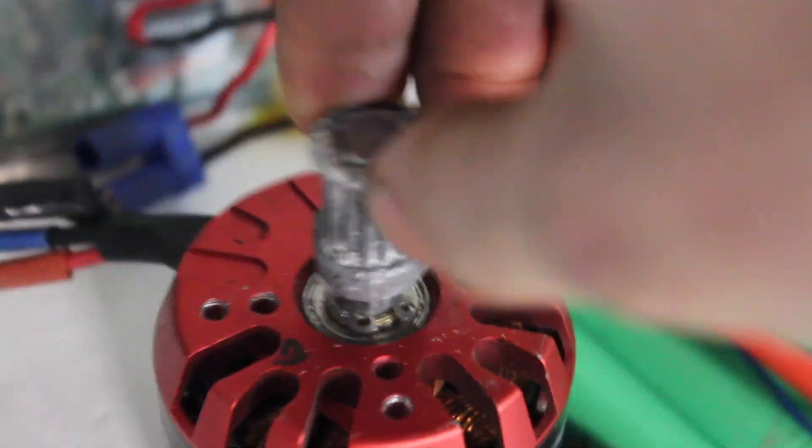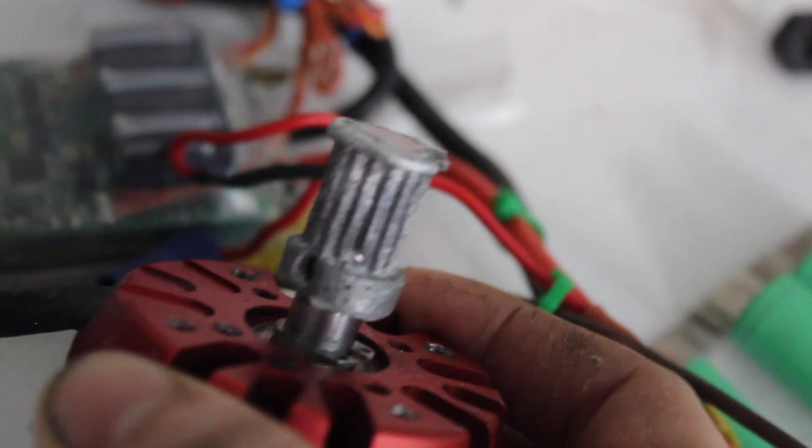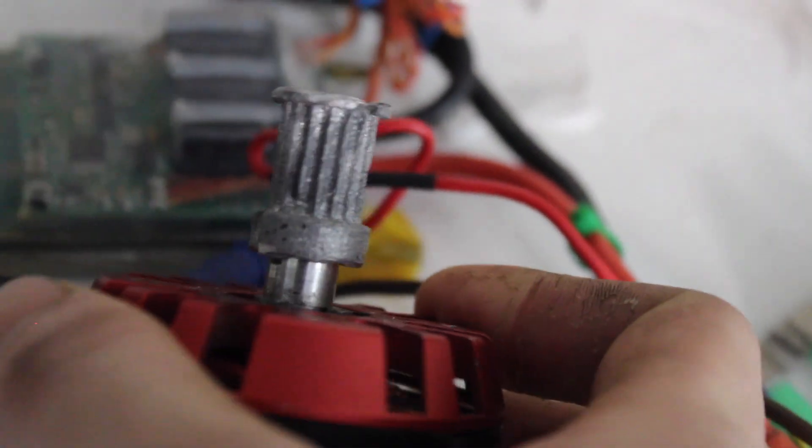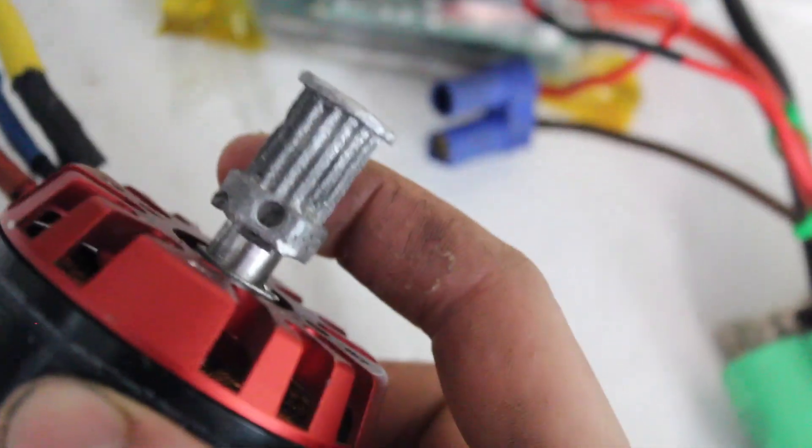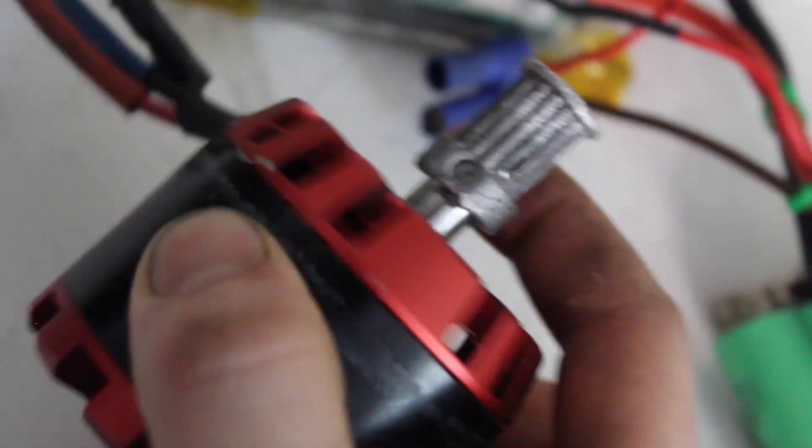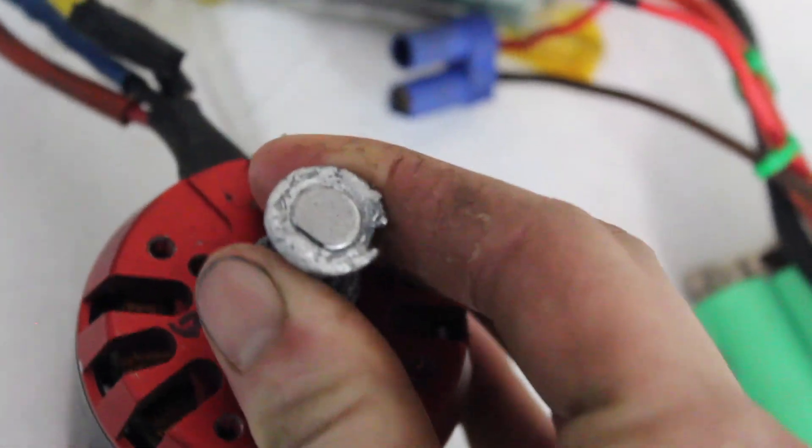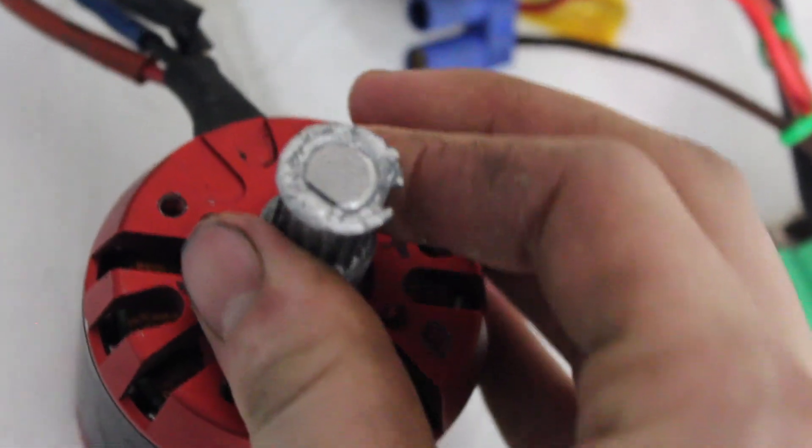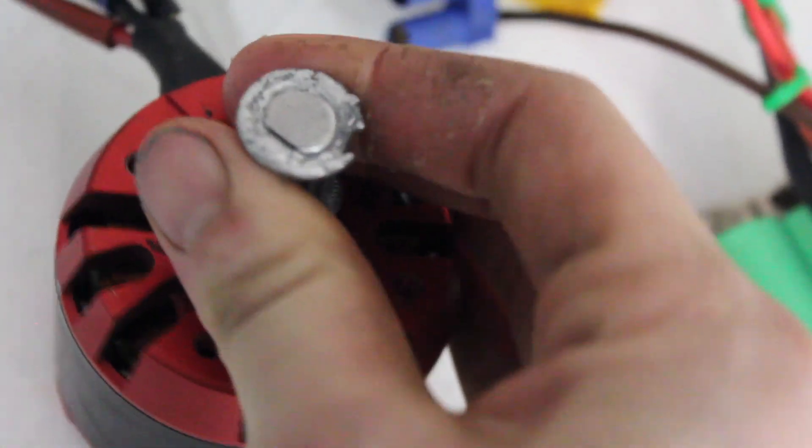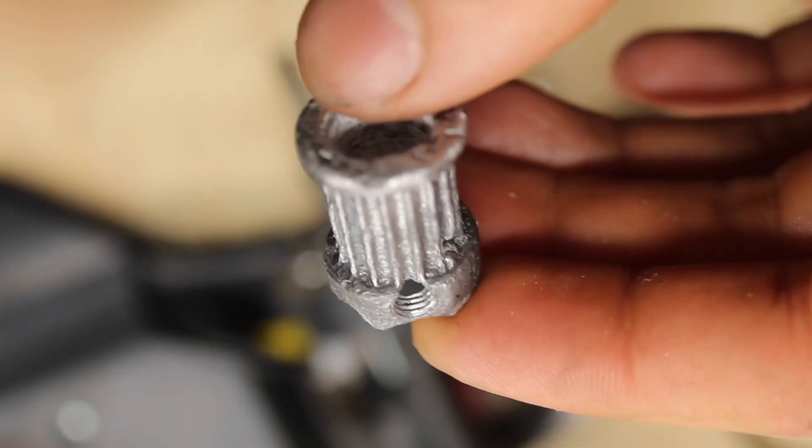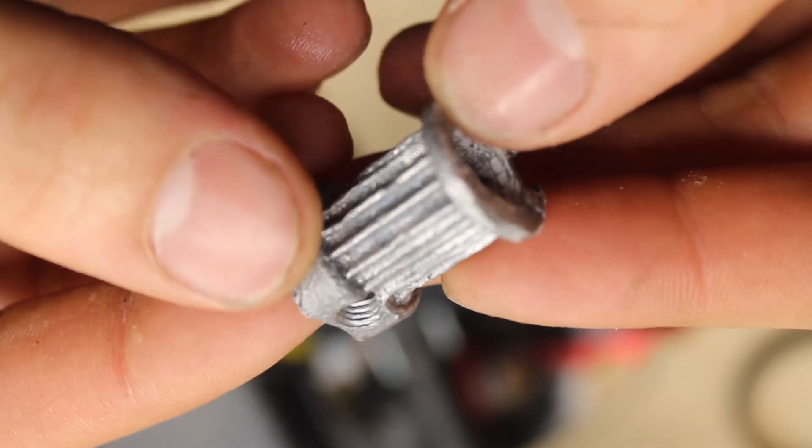I also was really worried about the tolerances because I've never worked with metal before. And I didn't know the shrinking. I think I did factor in the, I googled the shrink factor for the PLA or for all the different parts of it with the casting and everything. And I got super lucky and it just managed to get the tolerance perfect and I could just tightly fit it right on there. So that was one. I think it's like 5% for aluminum when you get shrinks. So I made it bigger. And it was really good. Because I was doing this over such a long period of time I forgot whether I'd added what I'd done for the tolerances and I did good.